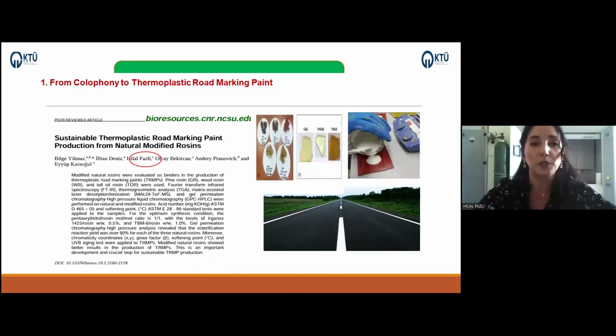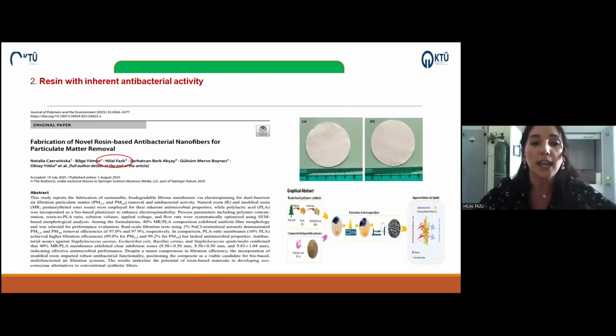For example, in this literature, we produced asphalt road marking paint using a material obtained by esterifying rosin with pentaerythritol, which has a high boiling point, and conducted various tests on this paint. The analysis results indicate that the paint we produced is of equivalent or even superior quality compared to paints currently used in our country. Moreover, this was accomplished using a sustainable and environmentally friendly product. And next one, we produced a filter from the esterified rosin using the electrospinning method and investigated its antibacterial properties. It was determined that the filters we produced exhibit high antibacterial activity.